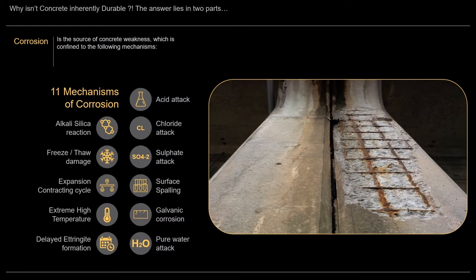So next time it gets wetted, crystals start to grow and expand and break the surface. Galvanic corrosion: if we've got two different types of embedded metal, then one will act sacrificially to the other. Even pure water is highly corrosive to concrete.